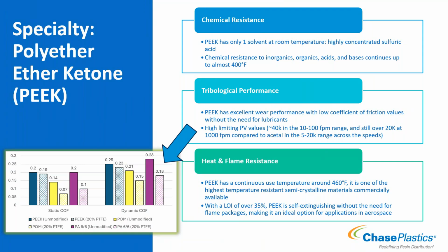The one nice advantage to PEEK would be that it has really high limiting PV values, limiting pressure velocity values. Wear performance can also be dictated by how much pressure you put on when it's wearing on whatever it's wearing on and how fast you're trying to get it to move. The higher the value, the more it's withstanding that and is going to be okay to be run at high pressures and high velocities. So if you're looking at slower speeds, the 10 to 100 foot per minute range, you're in the 40K limiting PV. And when you get to 1,000 feet per minute, really booking it, you're still at over 20K. To compare that to a different material, your acetal is in between 5 to 20K across the ranges, so PEEK is outperforming that if you're looking at using something with high speeds and pressures, and also temperatures, higher temperature performance out of the PEEK. So good wear performance, high temperatures.